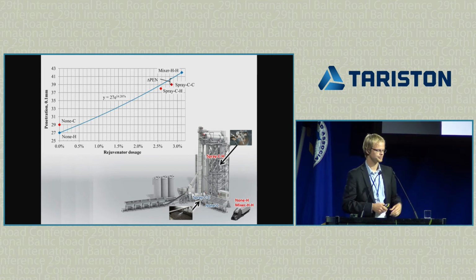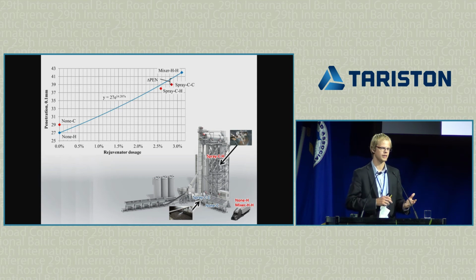And if I connect them with a line, I can say that if the only difference between any of my samples would be the rejuvenator dosage, the samples would align on this trend line somewhere. If there is some other effect, like aging in the drum, or losing some rejuvenator, the result would not be on this line. As we can see, the penetration difference between this line and the different samples is actually very small. It's about 1 to 2 decimillimeters. That's nothing, considering that we did all these steps: producing, extraction, measuring. So I can say that based on penetration, the addition spot didn't make a difference.